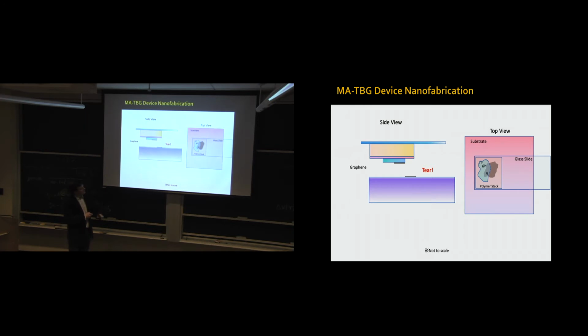From the top, this now looks like this: I have my substrate with half of my graphene sheet, and my glass slide with the hexagonal boron nitride and the other half of the graphene piece on top of it. Because these two pieces of graphene come from the same flake, they are crystallographically aligned with respect to each other, even though they're now at different heights.